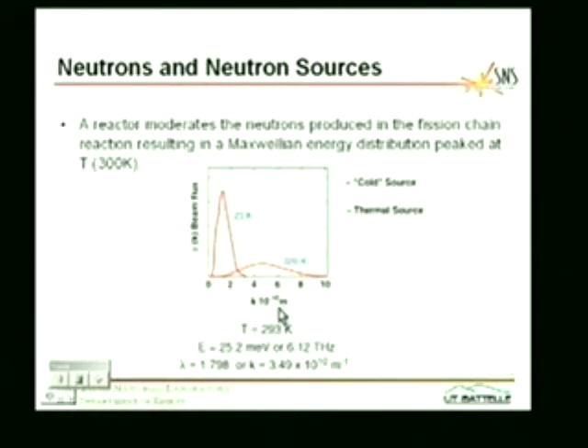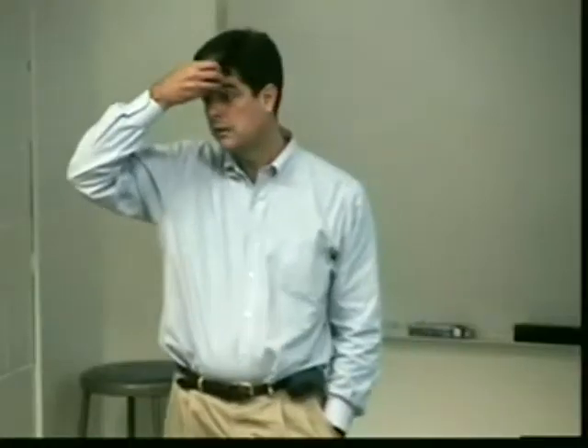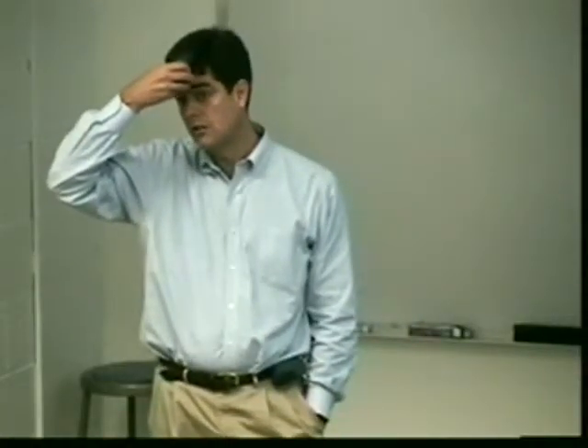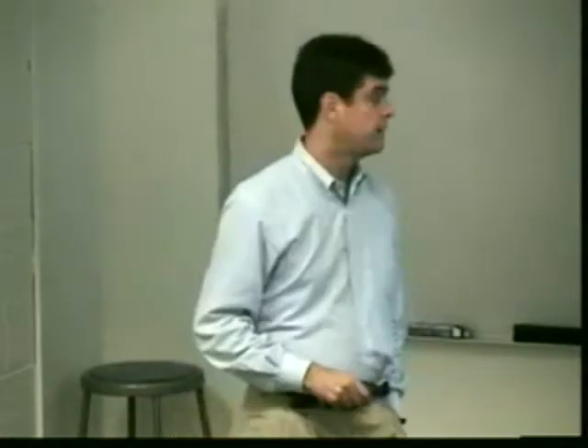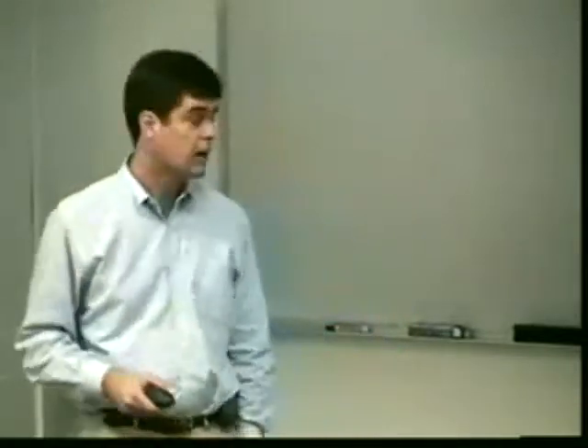So if you plug in some numbers, you find that the neutron that's the most populated, if you will, has an energy of about 25 millielectron volts, corresponding to a wavelength of 1.8 angstroms. And of course, 1.8 angstroms means the wavelength of the neutron is comparable to the interatomic spacing in materials, and that's why you can diffract.